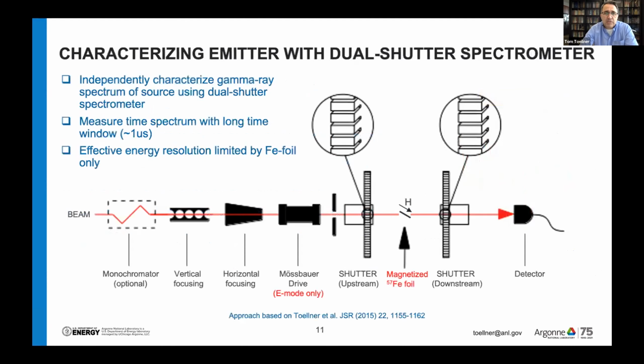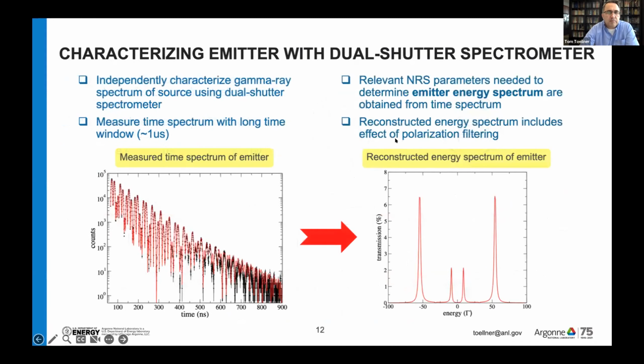Yeah. So I wanted to characterize the emitter more carefully to assess some things. And so I used the fast shutter spectrometer to do that. This is just showing the spectrometer with the magnetized emitter located between the shutters so that I could carry out the measurement. And this is the result of that measurement. I took a long time window time spectrum in hybrid mode, so I could measure easily out to 900 nanoseconds. And the red line is the fit of the data using CONUSS software.